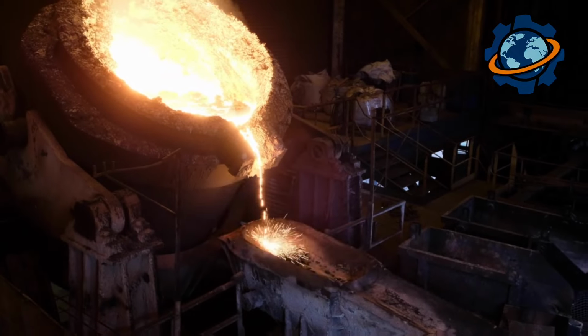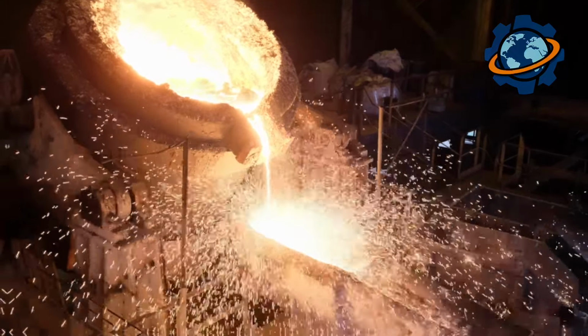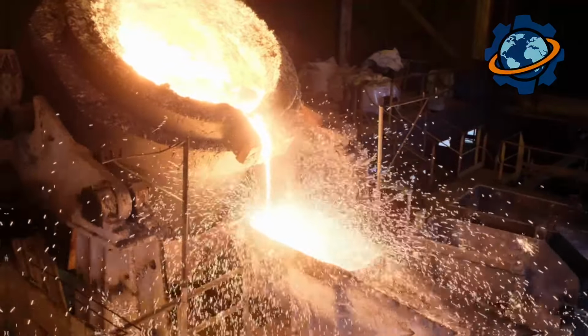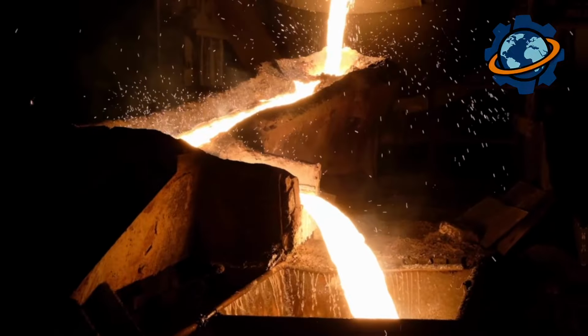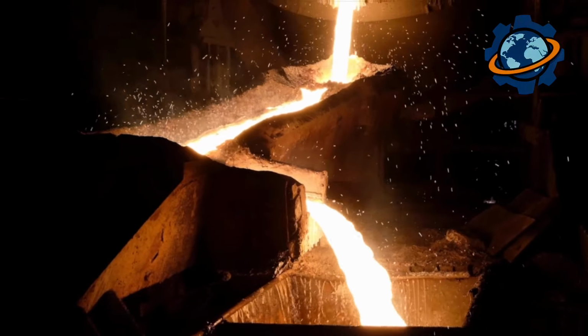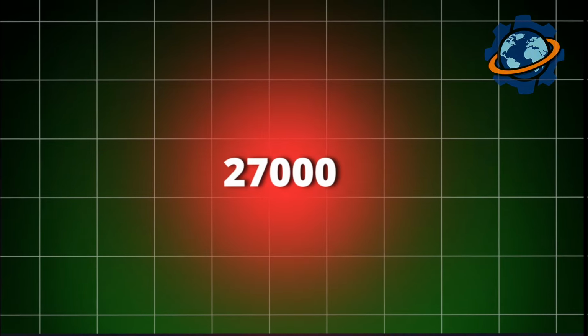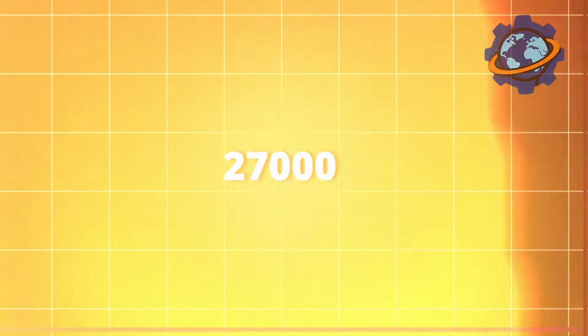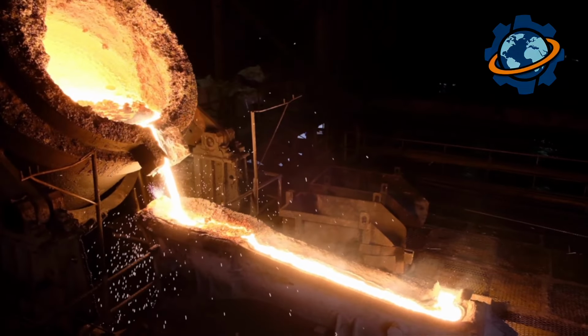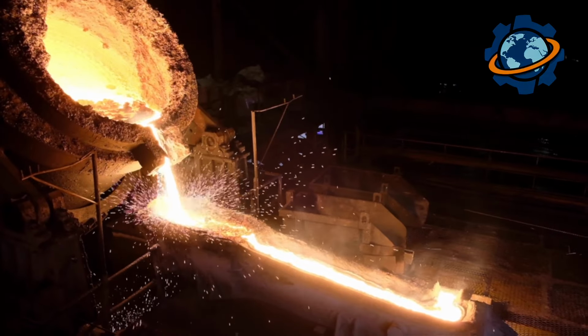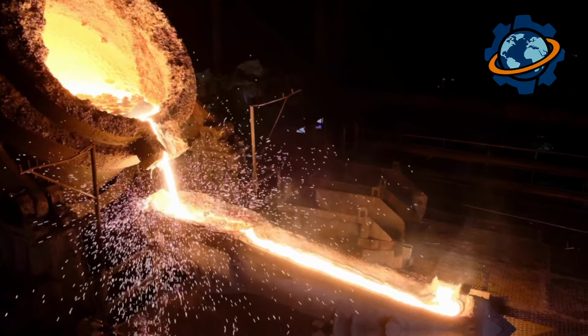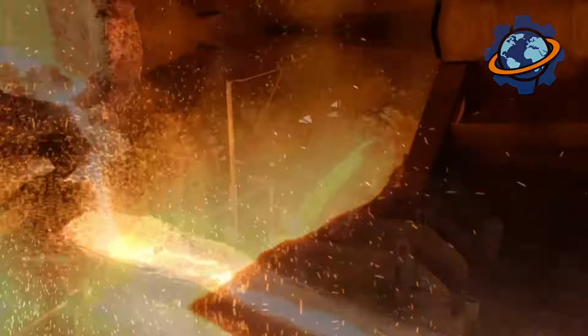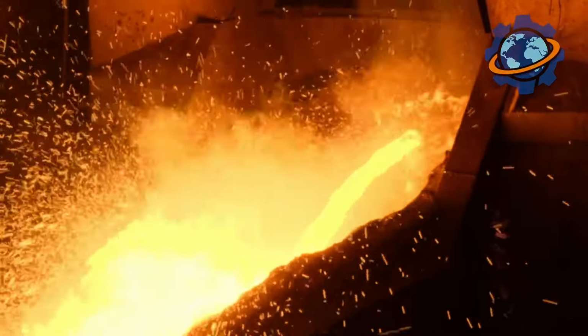And then they open the iron tap hole, and a dazzling, sparking stream of molten metal erupts with a roar. This is the River of Fire. The temperature of this stream is around 2,700 degrees Fahrenheit, 1,500 Celsius. It flows down special troughs, bathing everything around in a blinding light, and fills giant ladles that look like railway tankers. Each of these ladles holds hundreds of tons of liquid metal.